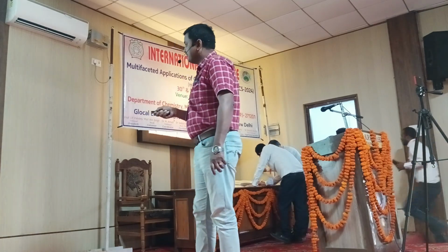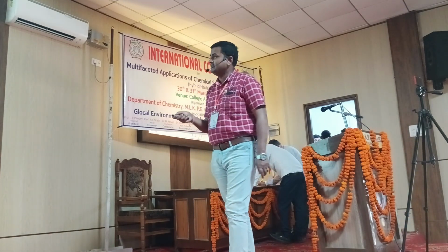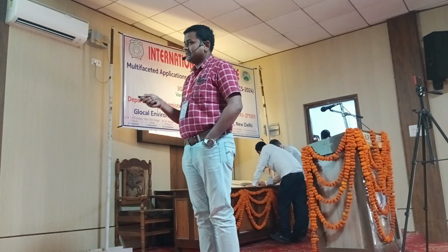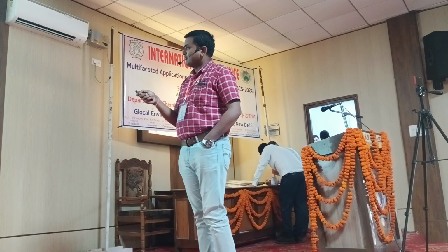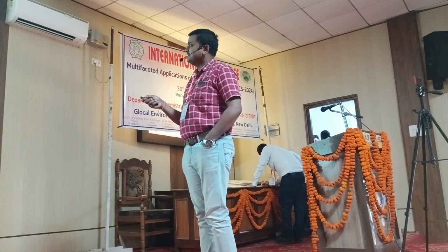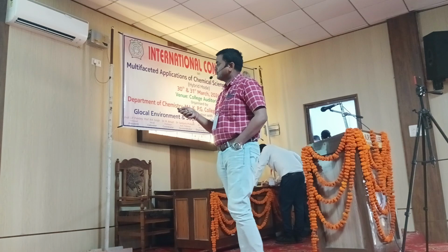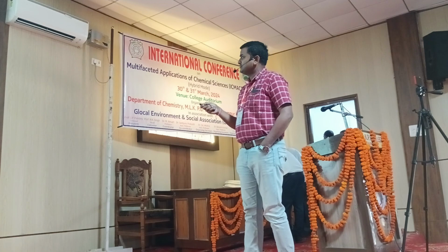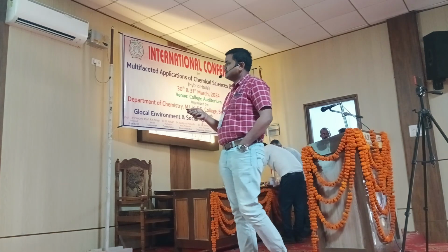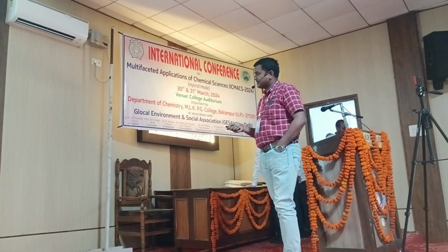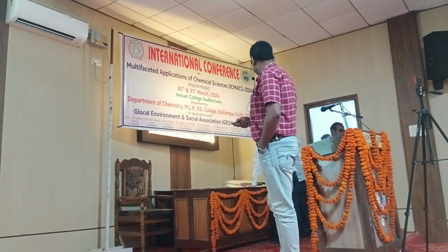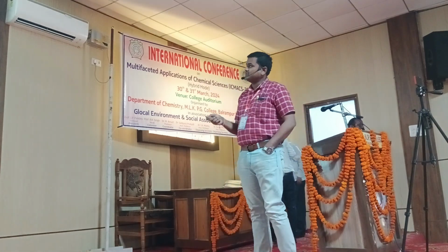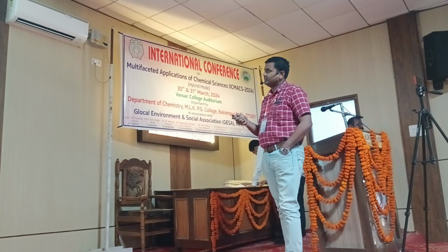That is why we are getting the white light emission in the case of ethylene diamine: one peak is coming from the monomer and another peak is coming from the J emission. We have calculated the CIE color coordinates, which are around 0.28 and 0.33, close to the perfect white light emitting coordinates, and the color temperature we have calculated is 8479 Kelvin.